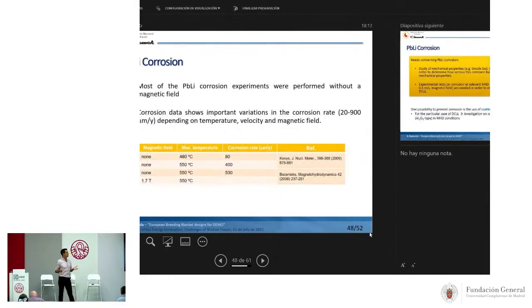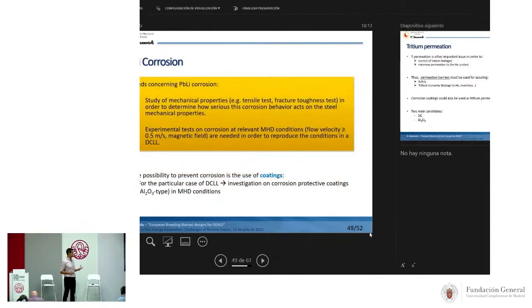However, most of the experiments on corrosion have been performed without a magnetic field. And as you can see here is a small example, but what is important to say is that this data presents a very large scatter in the results. So we need additional experiments to confirm all the behavior of corrosion with the materials.